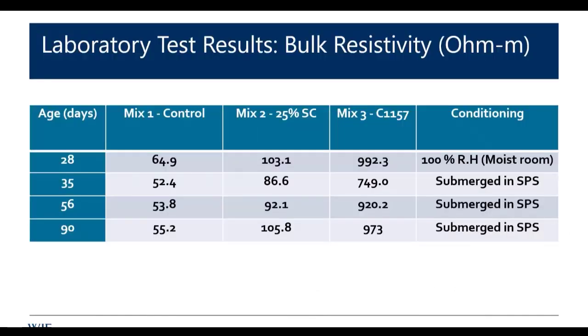So laboratory test results, this is a very interesting one. What we do is at 28 days, it was just coming out of the moist room. And then after that, it went into synthetic pore solution and we tested it out to 90 days. And what you see is what we would expect. Here we are with the Mix 1, and we see actually a nice doubling of resistivity with the 25% slag, as we would expect. And then it goes off the charts with the mix 3.